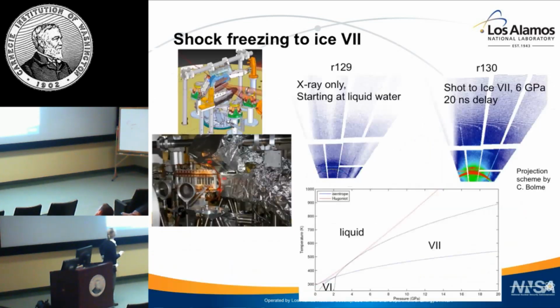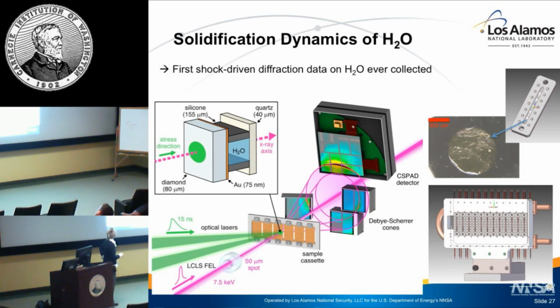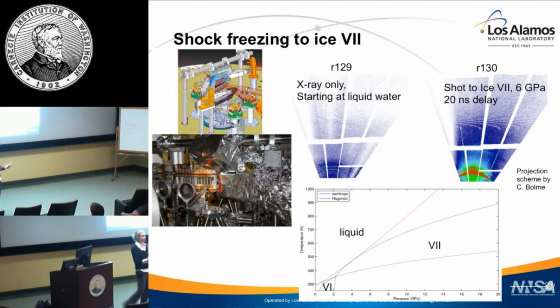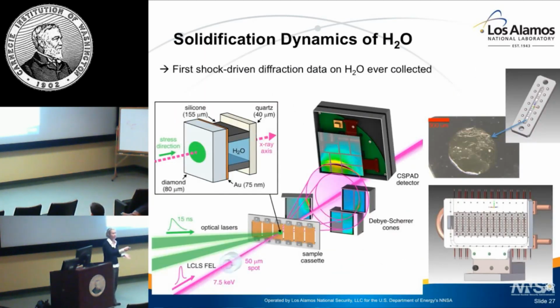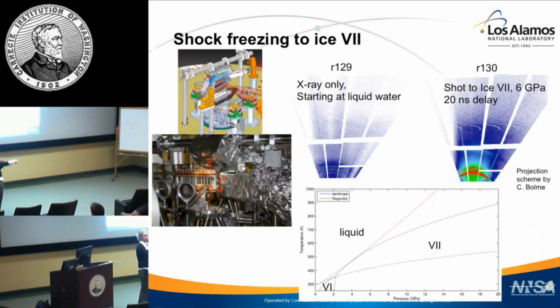CSPAD detectors are around. I want to draw your attention, this is a phase diagram, so temperature is a function of pressure. If I stayed on the principal Hugoniot, it would always be too hot, right? So I'd only see liquid. So we have to choose shock compression conditions that keep the temperature down. Okay, so we're going to do something called ramp compression, or extend out, stretch out the energy we deposit as a function of time over a longer period of time, such that we sort of slowly push on our sample, okay, and then probe what phase transitions transpire.